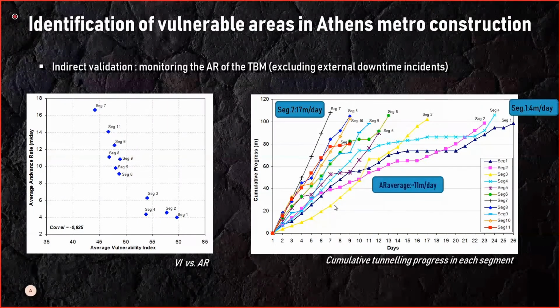In the second graph, you can see the cumulative tunneling process for each segment, and we can again see that the TBM drives the 100-meter tunnel in approximately 7 days in the case of segment 7, which is the best, and it needs around 26 days to cover the same distance in segment 1. What we can further see is that although we had classified segment 4 in a lower vulnerability state, it exhibits almost the same behavior as segments 1 and 2. As we have looked into it, we have found that there were actually some significant delays. You can see a plateau in the process, but these delays were from a collapse that was caused by the encounter of an old well in the tunnel.